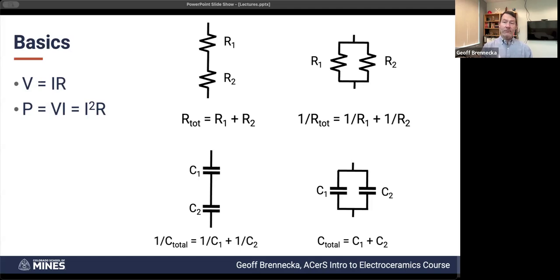Experimentally, you can, for example, go in with a scanning probe microscope, an AFM or a PFM or conductive AFM, and actually measure locally and see the distribution of conductivity, of permittivity of different things. There are other clever ways of doing this. You could put down microelectrodes and measure across a single grain boundary and those kinds of things.